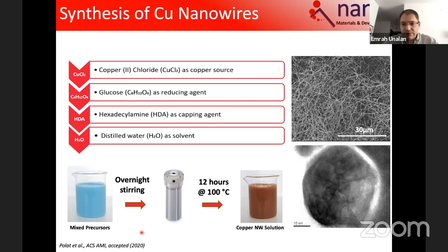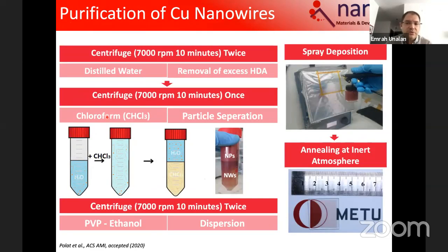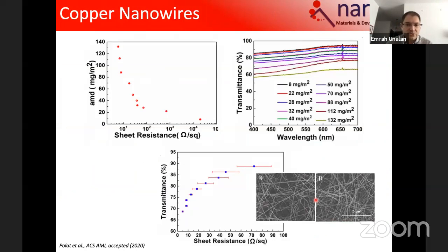And let me start first with the synthesis. This is again a solution-based synthesis. It takes place in an autoclave. You just mix up solutions and put into the autoclave. After 12 hours, you get the nanowires at the end. And purification needs to be there afterwards, as we did for the silver, and we spray coat this onto anything, as you see on the glass slide, of any size, to get transparent conducting films. But the orange color is there, in contrast to the silver, which was neutral in color. And similarly, we can control the sheet resistance and optical transmittance of copper nanowires as we did for the silver nanowires.